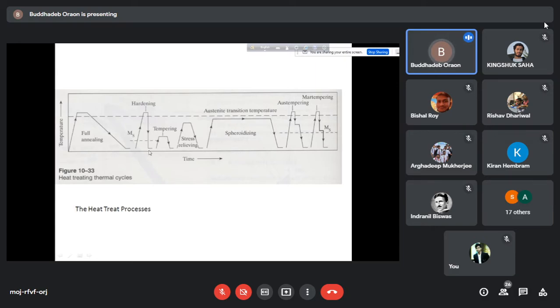So maybe it is water quenching. Just after taking it from the furnace, oil quenching or water quenching is done. The rate of cooling is very high. So this indicates the difference. Hardening means, as you have seen, that when you suddenly quench a material, the final microconstituent that will be formed will actually be martensite, which makes the material very hard. And this is how the three important factors are there: heating rate, soaking time, and cooling rate. These three parameters differentiate the different heat treatment processes.